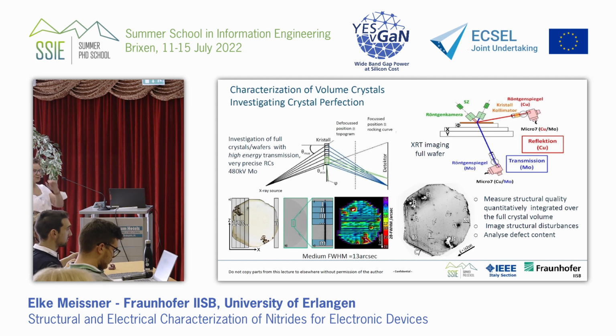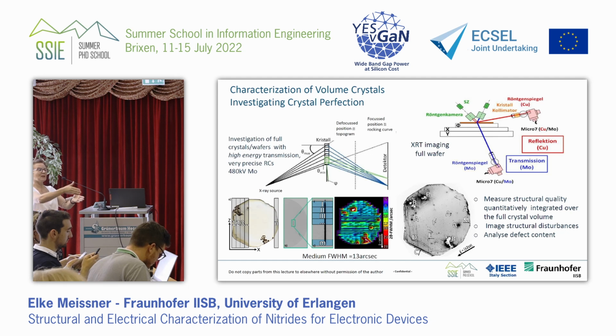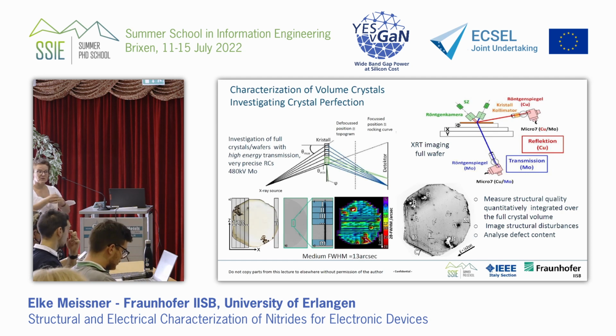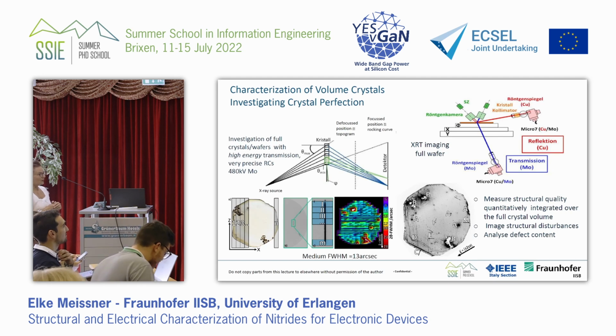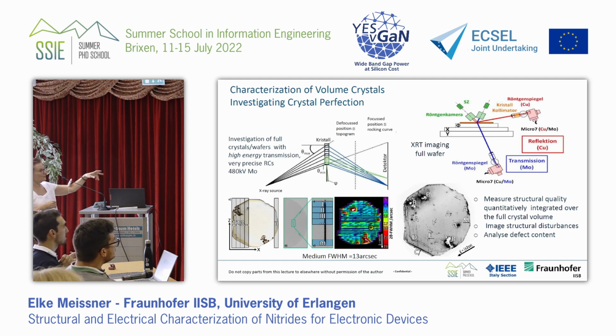So if you have a big crystal, which is such a piece, or even aluminum nitride or gallium nitride, which is a smaller piece, the gallium, for example, is a very huge absorber physically. So you cannot just shine with an electron beam, or an X-ray beam through the material, because it's such a strong absorber, you will see nothing. So we go to other methods which are more sophisticated, which is, for example, a high energy transmission Laue diffraction, which operates at a 480 kV molybdenum tube.